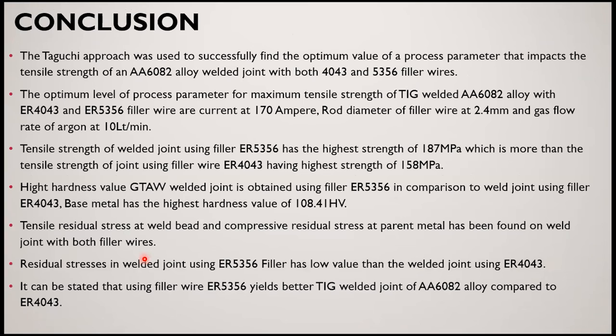We have successfully optimized the process parameters of the weld specimens with filler wires 4043 and 5356 with the help of the Taguchi method. The optimum level of process parameters for maximum tensile strength for AA6082 comes out to be 170 ampere of current, 2.4 mm diameter of filler rod, and 10 liter per minute of gas flow rate. This can be explained as when we increase the current, there is deep penetration of the oxide layer, and the liquid metal can go up to the root of the weld specimen and reach every corner, so that we are getting good strength.